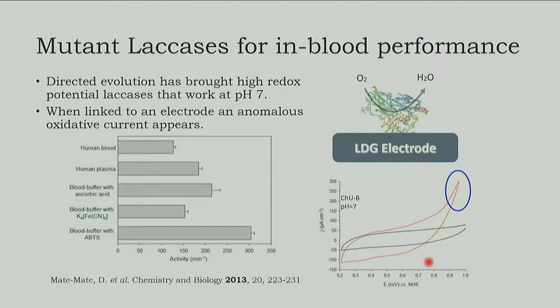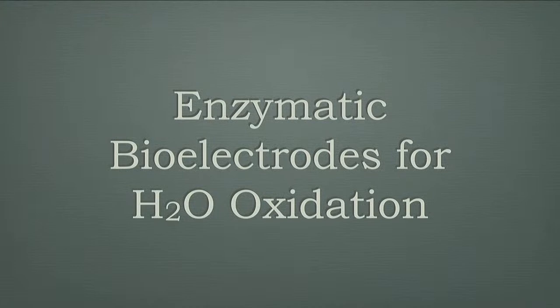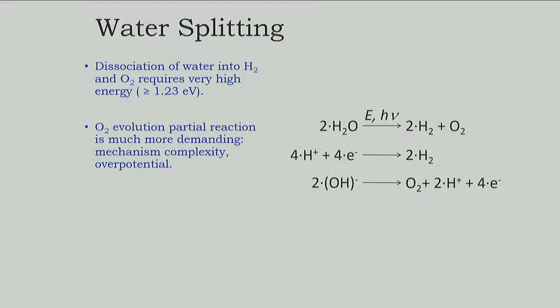How does it work? We were looking for this process here, the reduction, but we found something that never appeared ever before. And they said, hey, what is this oxidative current? Because these enzymes are not going to oxidize anything. And at this potential, we have tried many laccases before, and we never got this kind of signal. So this opened a new research line for me that is related to water oxidation, because we wanted to see if it is possible that this enzyme can oxidize water, or hydroxyl anions, to make even hydrogen peroxide or oxygen. We didn't find any other explanation for that signal there.